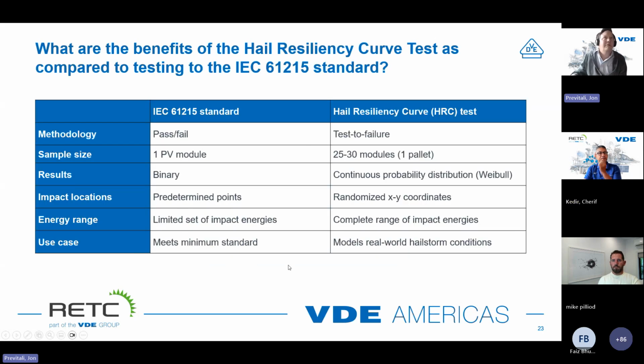Great, excellent, thank you. So can you go into a little bit more detail in comparing it to the IEC 61215 standard? Yeah, so with all standards, usually they provide a list of tests that are required, and then they provide some leeway in how the tests are performed. And in the case of hail testing, there's a very clear table in the standard, from as long as the standard has been around, at least in recent times, that has allowances for performing hail testing anywhere from 25 millimeters, which is 1 inch, all the way to, I think, 75 millimeters. But the standard never required anybody to pass hail greater than 25 millimeters. So every manufacturer did what every manufacturer would do: pick the lowest, easiest test, pass it, and move on.